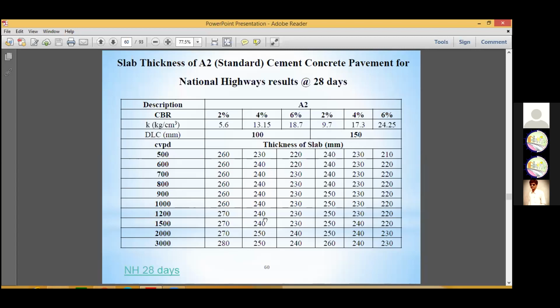K is in kg per centimeter cube. So it's readily available. DLC I assume 100 and 150. CVPD 500 to 3,000, and we find based on the design and the criteria fulfilled in the particular design, the thickness of the slab 260 to 210. You refer to the left hand side 260 and the right hand side the 6% 210. Based on this whole work, 210 to 260 mm thick, the slab thickness we use in a standard concrete.